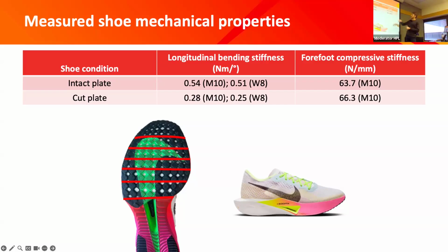Interesting to see though that it didn't have much of an effect on the linear, or axial, compressive stiffness of the shoe in the forefoot. So in the intact plate condition it's about 64 newtons per millimeter of stiffness if you just squish the forefoot, and it went up to about 66 newtons per millimeter in the cut plate condition. So slightly stiffer, but not a huge change there.